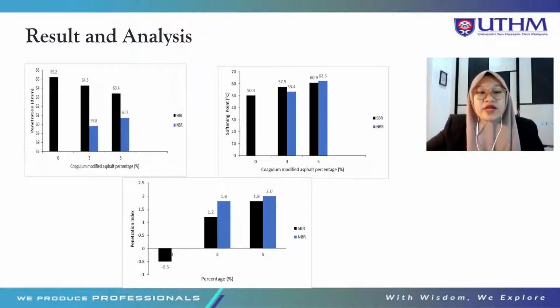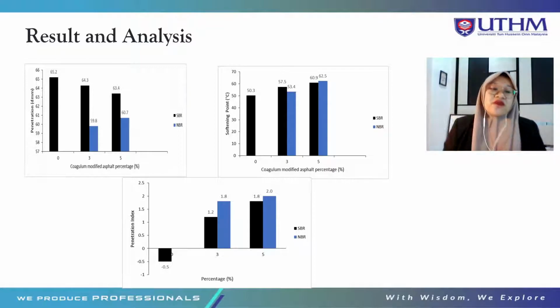The softening point values of the base binder were increased by 14.3% and 21.1% respectively with the addition of 3% and 5% SBR. The softening point reached 60.9 degrees Celsius with 5% SBR added. As for NBR, the modified asphalt binder with 3% NBR had a softening value increased by 6.2% compared to the base binder with 0% NBR added.